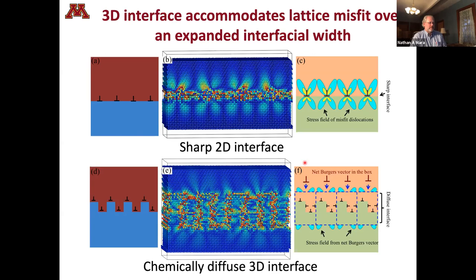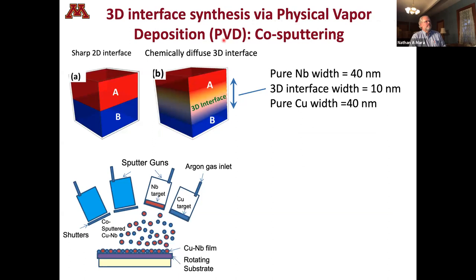So how do we make these? Well, we grow these in a magnetron sputtering chamber, but instead of doing a 2D interface, now what we do is we grow our pure phase, maybe it's niobium. We gradually turn on our copper source and turn off our niobium source to grade our 3D interface. There's a lot of different knobs we can turn when we do that. And then we end up with a pure copper phase above that. And then you repeat this again. You turn one target off, turn one target on. Very similar to what we did with the 2D interface copper niobium.